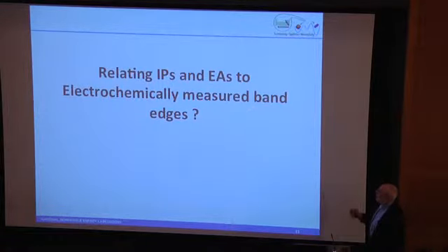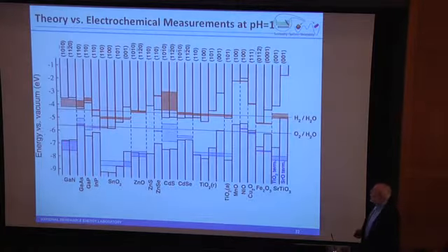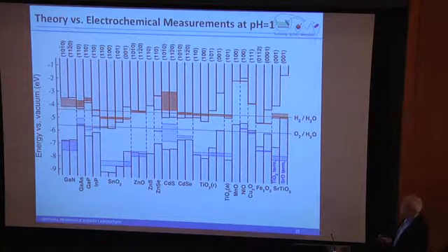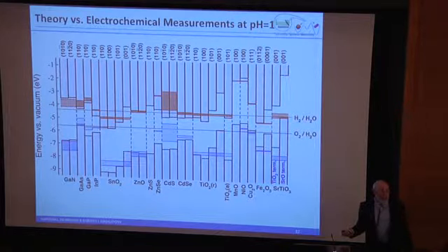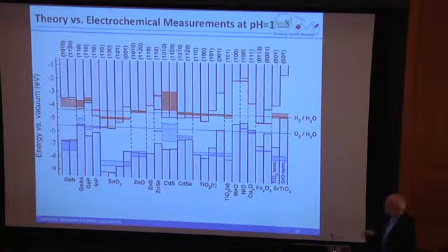So can we relate what we showed you in the photoemission data to electrochemistry? The answer is, actually it works pretty well. So this shows you the hydrogen and oxygen potentials mapped against where these energy levels are. And these are the band edges. And this is the experimental data, versus the theory data. And so we know which systems split water, and so far we have a pretty good concurrence on which systems ought to split water and which do. We're pretty good on where the potentials are, but there's some mismatches that we have yet to solve. So some systems are pretty far off.